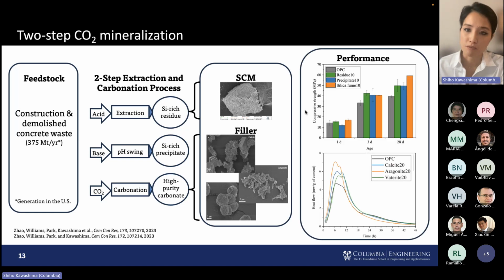So the SCM, the silica-rich residue, we tested it. We tested the precipitate and the residue, and we see it doesn't outperform silica fume, because silica fume is just such a pure form of silica. But we do see that there is a pozzolanic reaction, with an increase in the long-term strength gain. And with the high purity carbonates, there are three polymorphs. We'll talk about this in detail; this is just giving you a glimpse. But because of the distinct morphologies, even though they're all calcium carbonate, they affect cement hydration kinetics differently. So there is going to be an impact on the cement-based system.